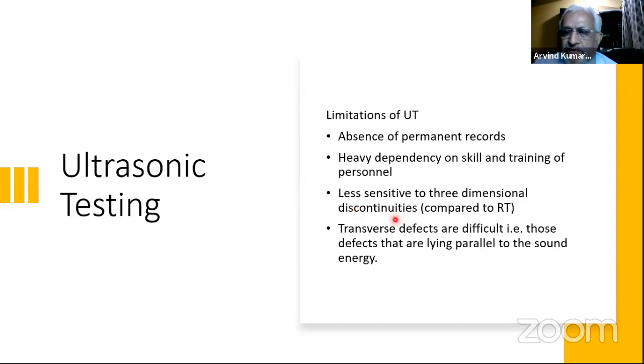Less sensitive for three-dimensional defects compared to RT. Porosities and all can be easily picked up in radiography, whereas some porosity clusters, being small, sometimes get into the noise level of the instrument and may not be picked up. Transverse defects are difficult. For defects lying parallel to the surface, the defect has to be perpendicular to the sound beam to have the best amplitude. If it is parallel, you will not be able to pick it up.